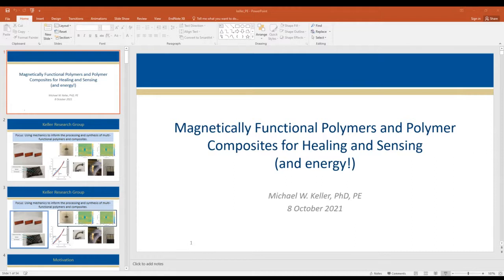We have a pressure cell that we built. We put a sample in there, apply pressure on one side, and measure the output. If we apply 100 psi and there's 0 psi on this side, gauge pressure, relative to the atmosphere, then that's 100% heal. Good to go. This is a closed volume. If there was a leak, this pressure would slowly increase over time as gas leaks from one side of the membrane to the other.